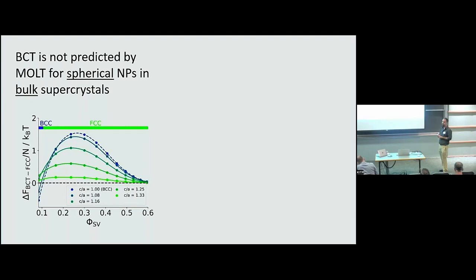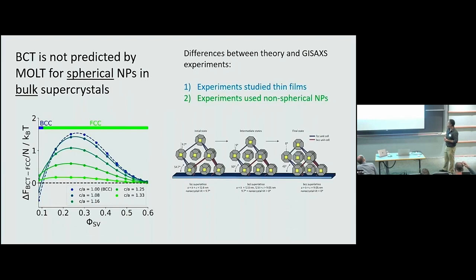And that was bad at the moment because that was not what you see in the experiments. So we decided, instead of just quitting, to look at the difference between the experiments and the theory, asking the question, what is the difference? At this point, we were doing calculations for spherical nanoparticles in bulk superlattices, and the experiments are done for thin films, and also, of course, the nanoparticles are not spherical. So we tried to look at these two differences individually to see if one of them can explain the formation of BCT.